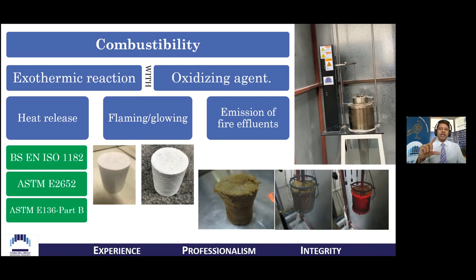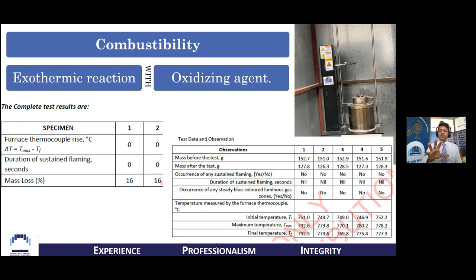What this test does is that we have a vertical tube furnace, which is maintained at a temperature of 750 degrees Celsius. And as the temperature is maintained and stabilized, the specimen is lowered. You can see a specimen on the bottom right corner of your screen, before it is loaded into the equipment and when it is just brought out burning. This is lowered in and kept in this vertical tube furnace. And we assess the mass loss, the temperature rise, and if there is sustained flaming of the material to arrive at quantification of the property of combustibility. And mind you, this test is only done for any product or material which is homogeneous in nature and not something which is non-homogeneous.